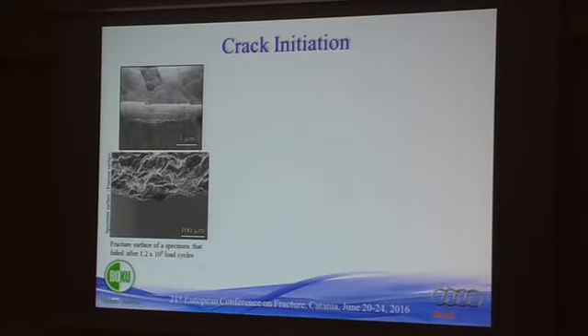Because of that, we assumed that the cracks might be initiated by slip bands. And we took a closer look at the specimen surface. Please note this is the specimen surface, this is the fracture surface. And we indeed find some slip bands with even some micro cracks emanating from the slip bands. But still, we were not that sure if these slip bands were the result or the cause of the failure.